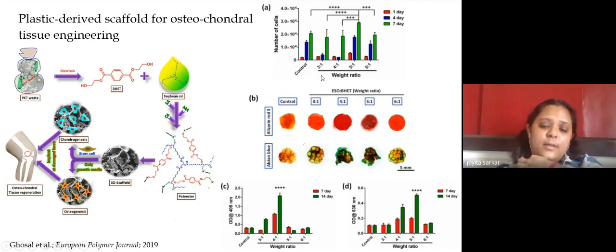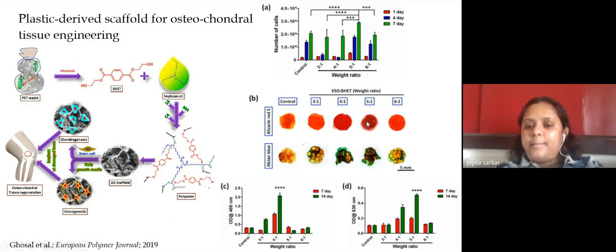And then what was done is that the osteoblasts and chondrocytes, that is bone cells and cartilage cells, were grown on the scaffold, and it was checked how is their functionality. So the bone cells, obviously they produce lots of calcium phosphate, and alizarin red is the stain which stains calcium. So you can see how beautiful red color is produced in this 4:1 and 5:1 scaffold. So that means the bone cells are quite functional and doing good in this scaffold.